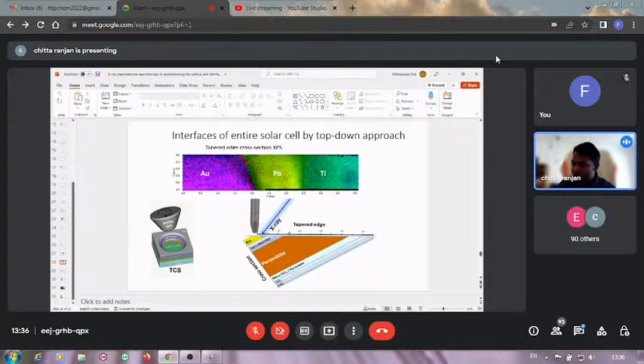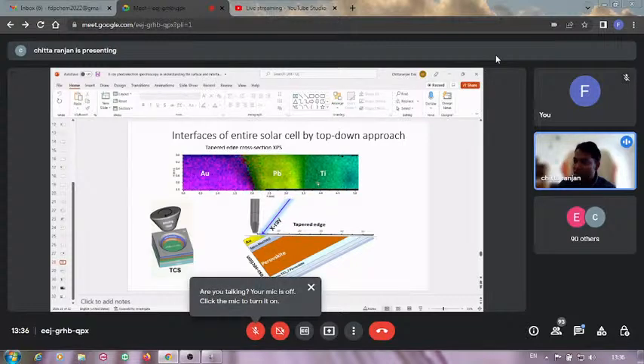For example, this is a device that is gold, spiro, perovskite, and titanium dioxide, and here you can see when you measure here, that's what I was telling about the imaging. Here you can get like gold, and you know this layer is mostly gold, and this layer is mostly lead, and this is mostly titanium dioxide. So from here we can say, okay, if not only lead, if you measure carbon and other things, then we see, okay, this is perovskite, and this is completely gold, and this is titanium dioxide, and so on. So this gives information about what is what and how the image looks like.